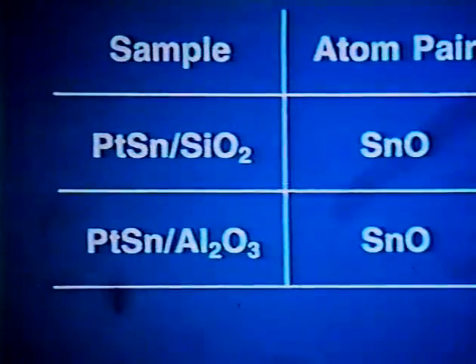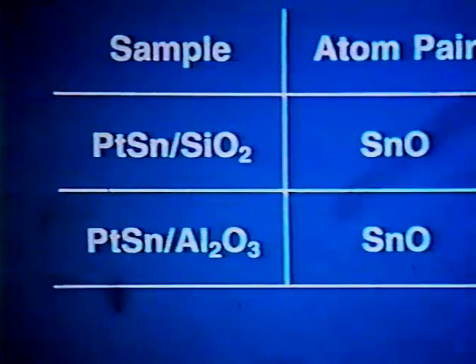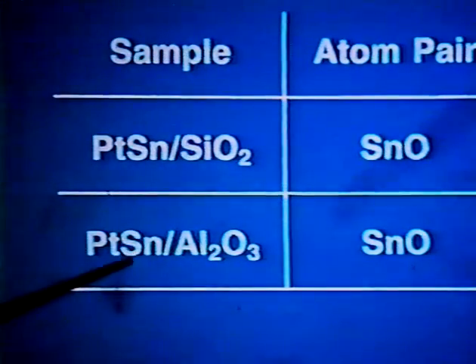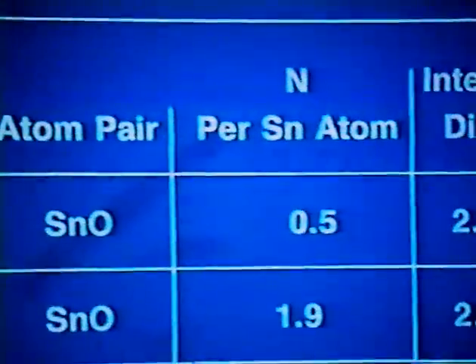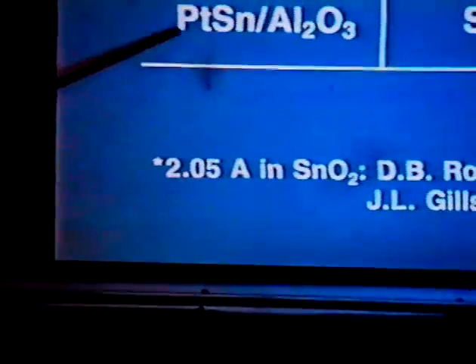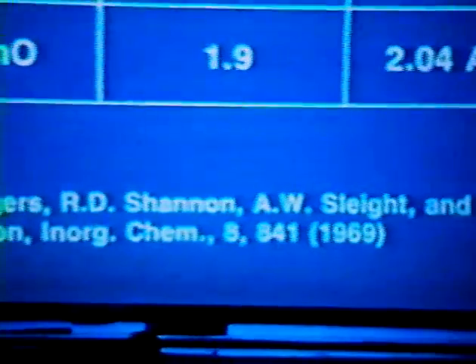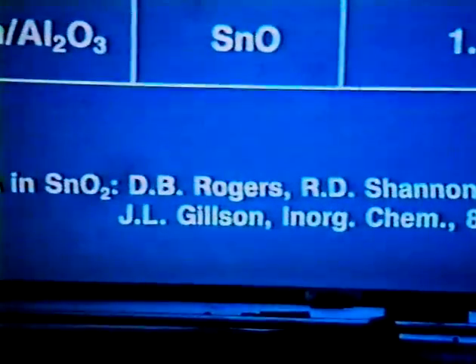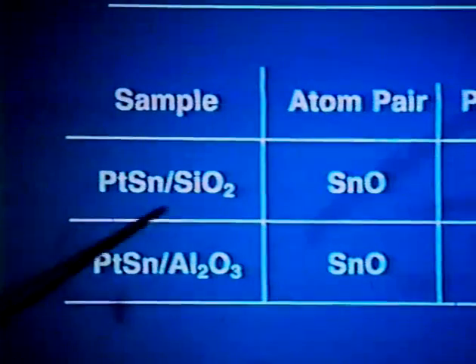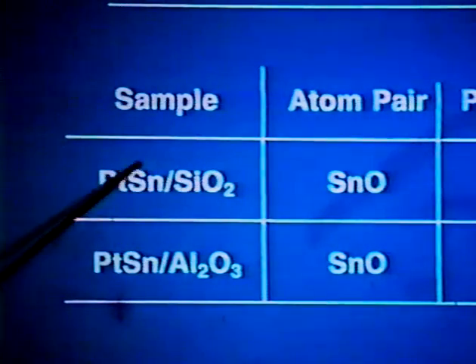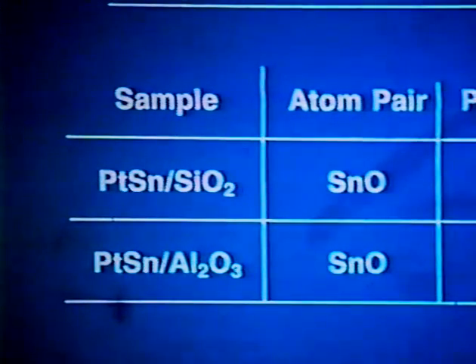Just a quick clarification. You said something about the reactivity of these catalysts. Are you saying genericity of those compositions, or do you mean specifically that these preparations were tested? You mean the catalytic activity, of these particular samples, or generically those preparations? Either one. Platinum tin alumina is a commercially used reforming catalyst. Ours did not necessarily reflect the composition of the commercial catalyst, but this was prepared according to a patented route, and it's likely that the patent we followed is approximately the procedure that's used to make the commercial reforming catalyst. But you did not test the activity of this specific prep? No, not for reforming. This one over here doesn't follow any known commercial prep, and for those things for which we did check its catalytic activity, it is very poor.